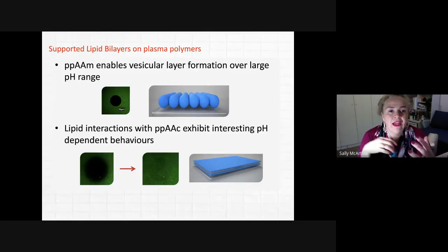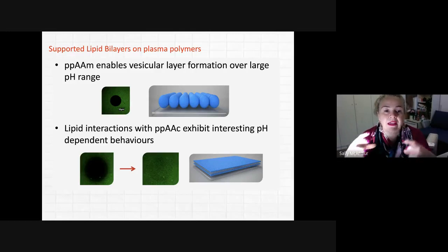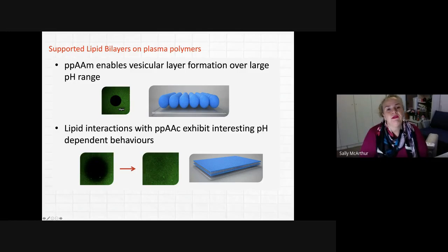So we've got a way, using these chemistries, of creating a packed vesicle layer, or by changing the chemistry and using that pH shift, we've got a way of actually, on an acrylic acid surface, making a lipid bilayer. And so the interesting thing here is if we use a FRAP technique, so we use fluorescence recovery after photobleaching, this tells us about whether the lipids are mobile on the surface.